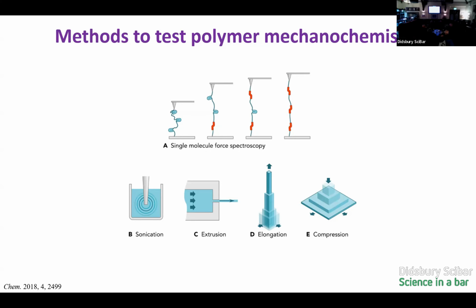So it's a difficult experiment, but it gives you incredible information when you think about the mechanophore structure and the forces it needs. Lots and lots of information, but not necessarily something that scales, right? Because we're never really going to be looking at a single polymer chain when we use them. The most commonly used technique in the lab is sonication, so essentially providing ultrasound energy to your solution. It causes these voids to be created in the solution, and as they collapse, they pull the solvent and the polymer chains with them, stretching out the polymer. And we'll have a look at that in a minute.